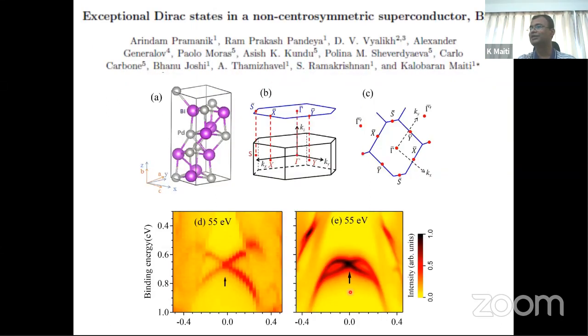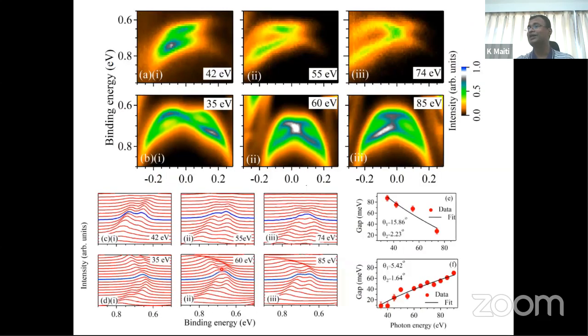Now we clearly see that this is the Dirac cone. This is one K vector, this is another K vector, and it shows that the bands are crossing. Okay, there is no gap at 55 eV. Now we can change this photon energy and see what is happening. I should be a little faster because there is no time.